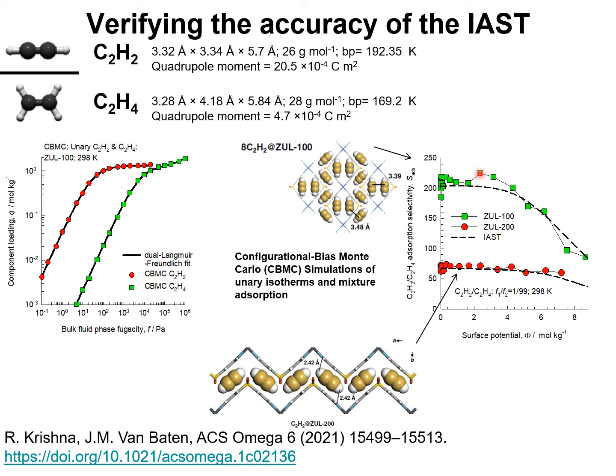The CBMC simulations shown by the symbols are in excellent agreement with the IAST calculations with adsorption selectivity calculated from the corresponding unary isotherm data fits.